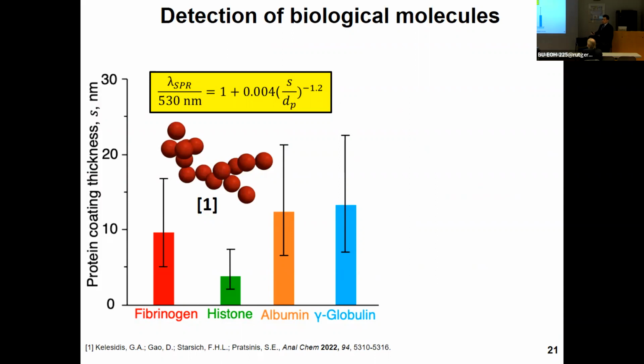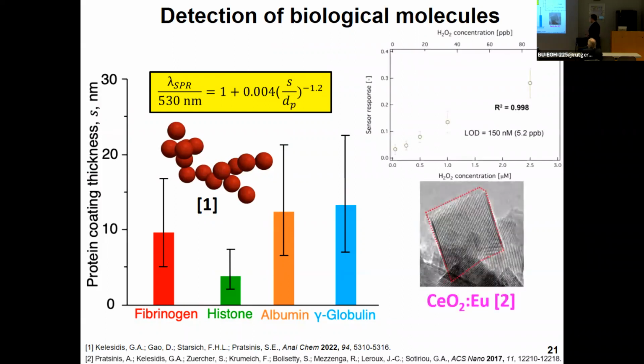And in addition to gold, one of the nanomaterials that I have worked with, but the last one that I will show you for today, is cerium dioxide. So in the beginning of my PhD, I worked with metal oxides, such as cerium dioxide, and I doped them with europium, a luminescent material, as I mentioned earlier. And by making this very unique composition of nanoparticles, we are able to design a sensor that can detect hydrogen peroxide in biological media. In particular, this sensor was able to detect hydrogen peroxide down to 5.2 parts per billion.